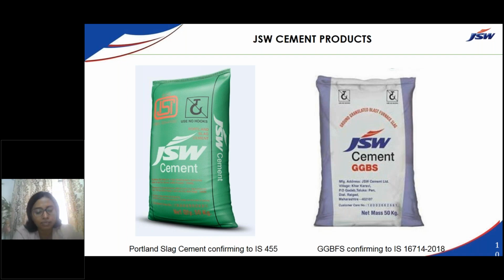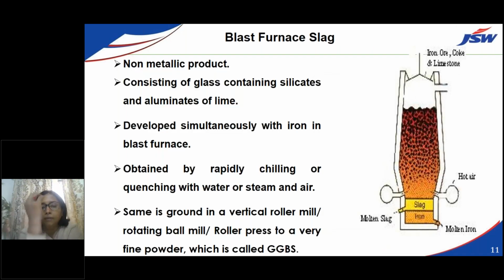If somebody is interested in trade products, we have other product variants like Concrete HD, that is also a Portland Slag Cement, but for people who want immediate quick deshuttering, they can use that product with high strength. We also have composite cement, which is IS 16415 compliant. Along with that, we have raw slag. Raw slag can be used as a replacement of sand. So 25% to 50% replacement can be done for the coarse and the fine aggregate part.